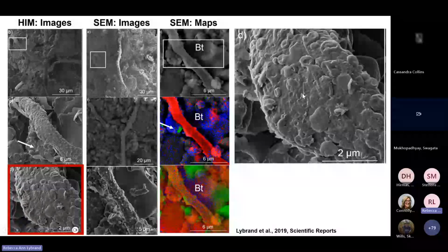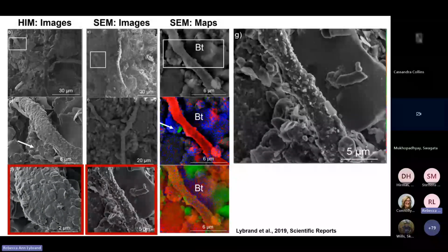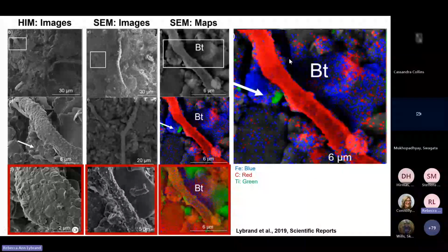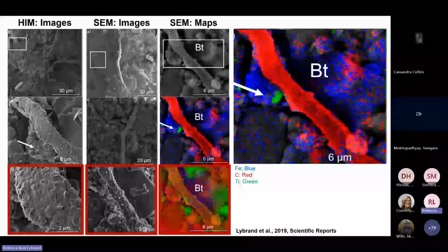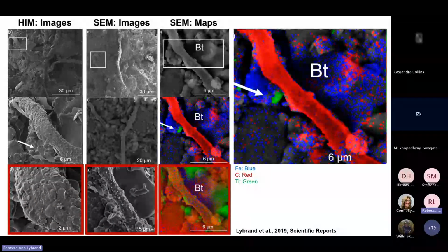But going to that same interface with the scanning electron microscope, we were able to see that this fungal structure is associated with biotite, and this aggregated material actually did not have any kind of organic compound. We thought this may have just been organic materials associated with the fungal structure. Instead, it was actually mostly iron as well as some titanium. So that leads to additional questions of, is this some kind of biomineralization process, or what's going on here? But this just provides a lot of insight. And being able to co-locate using different approaches is highly effective for getting as much information as possible.